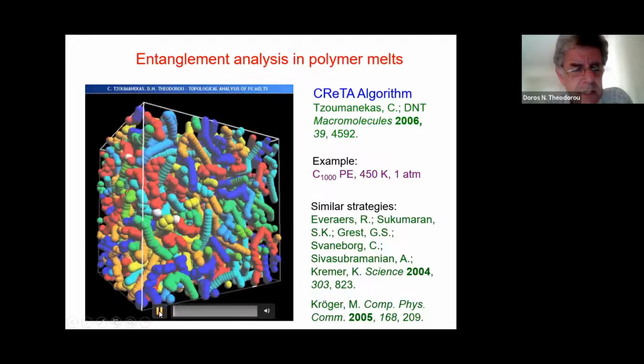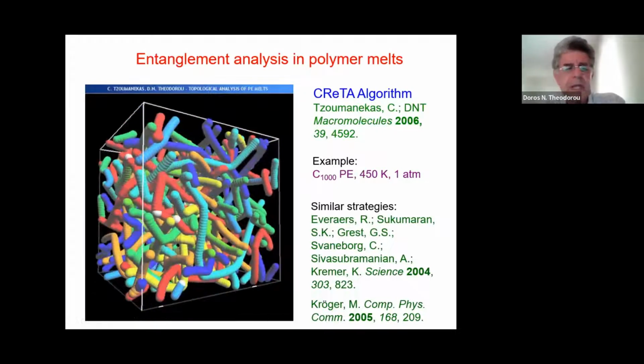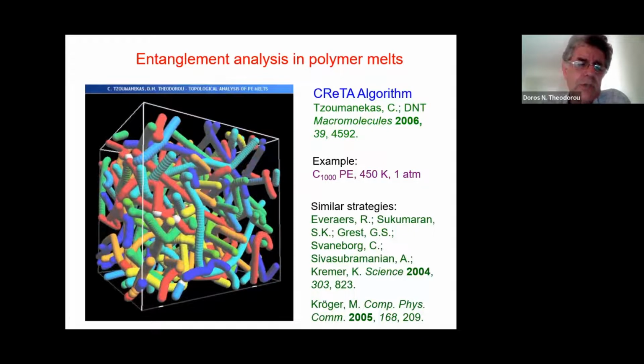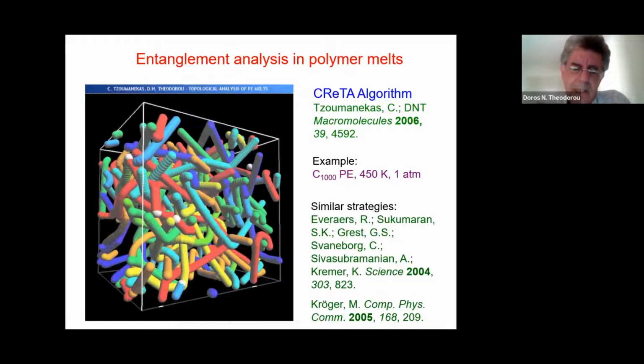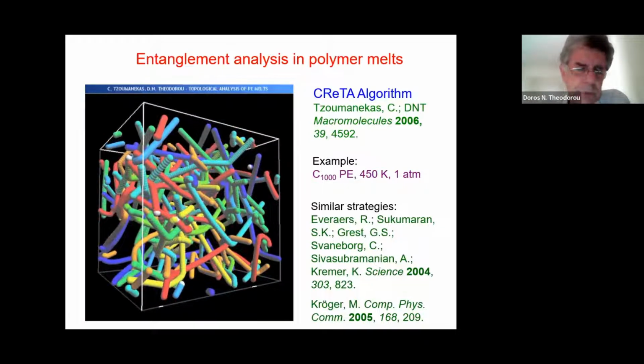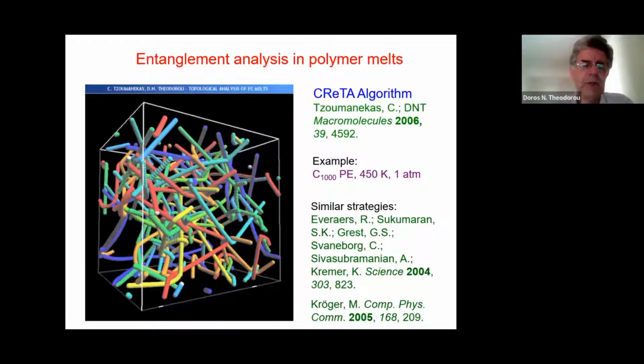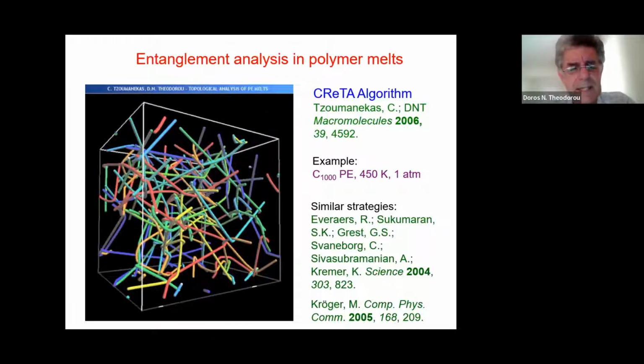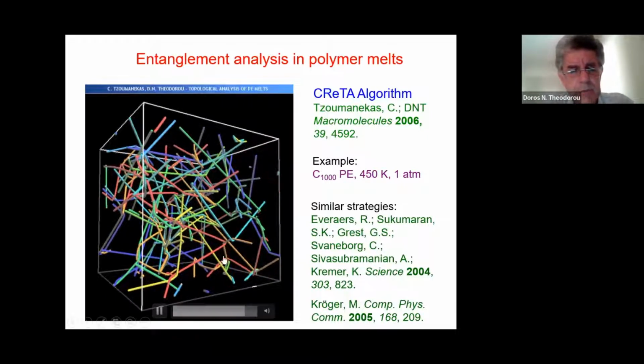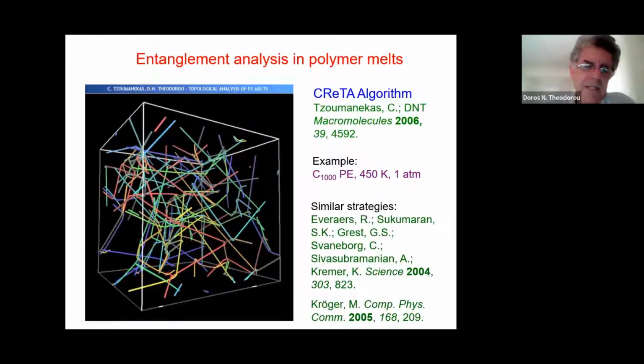And then it proceeds to reduce the contours of all the chains present under the condition that no two chains can cross each other. And as the reduction proceeds, the diameters of these chains are also reduced. So in the end, the atomistic configuration becomes a set of zigzag lines coming together at topological constraints with a coordination number of 4. And these topological constraints are our picture of entanglements, and the zigzag lines that go through them are our picture of the so-called primitive paths that were envisioned by Sam Edwards in connection with entangled polymers.